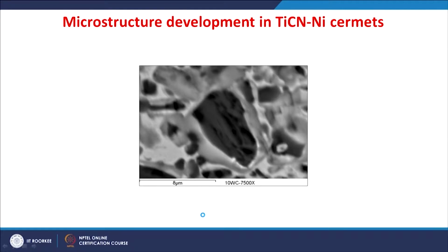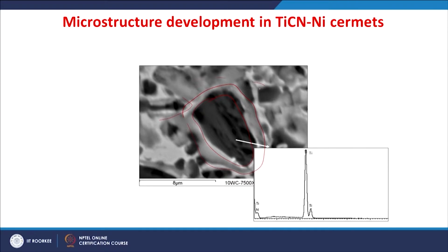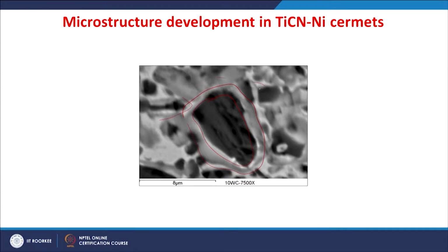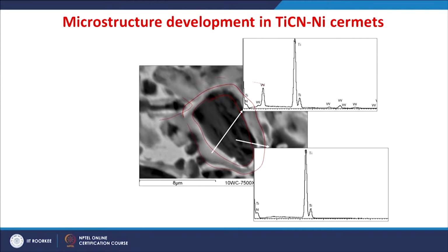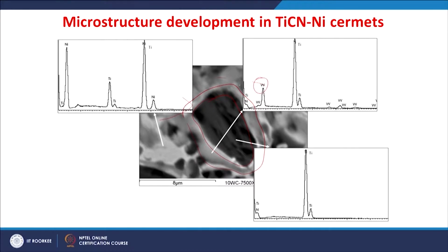So, after sintering, the microstructure looks like this. There is a black core region, and then there is a shell generally called the rim region, and then attaching this is the binder phase. The black region is a core, whereas this gray color region is a rim, and then the brighter region is the binder phase. So, EDS analysis of these three different phases indicates the core, which is black, is rich with titanium, whereas the rim region also contains, along with the titanium, the tungsten, and the nickel binder phase, which is a bit brighter in contrast, has nickel and titanium.